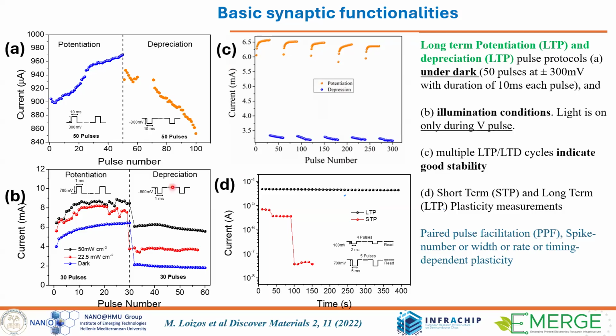Then, of course, we can tune these potentiation depression protocols with light illumination. The blue data are here, in black, in dark configuration, while when we increase light illumination, we can tune the conductivity. Also, we demonstrate other protocols like short-term plasticity, long-term plasticity, PPF, and other types of plasticity.